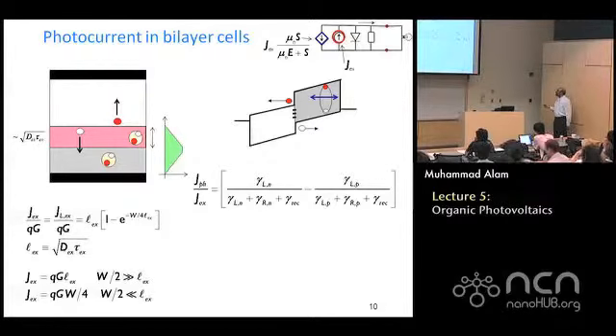This is the flux of electrons going to the left contact, gamma Ln, and I have this recombination that's telling me the recombination with this quantity, with the holes. And I have gamma Rn, any flux that can jump over the barrier. Now, most of the time, the barrier is so big, I'm going to ignore it. So most of the time, I shouldn't have to worry about that term. So I drop that term.